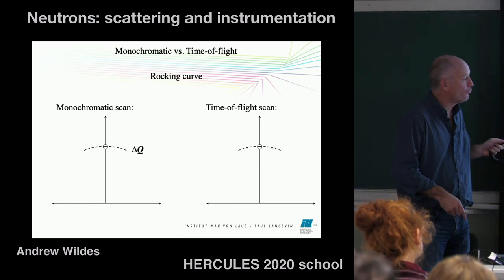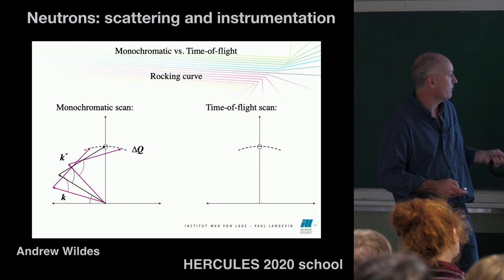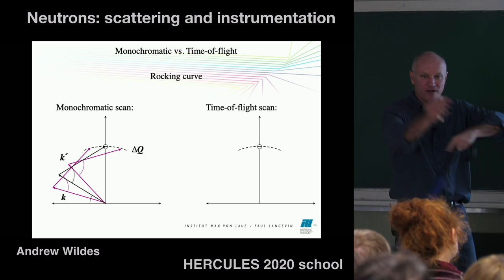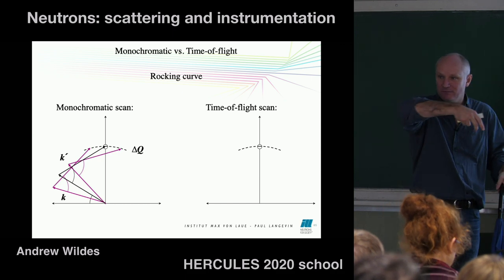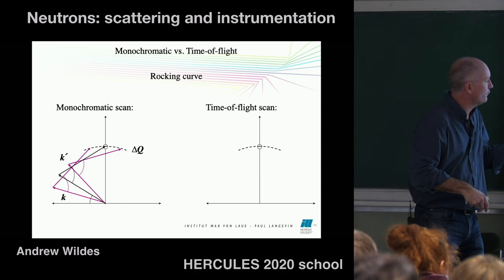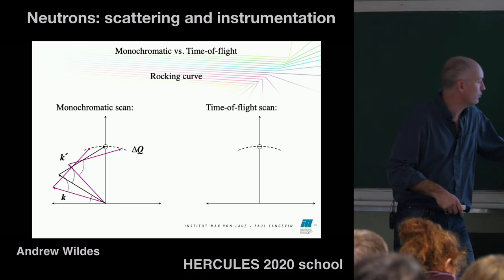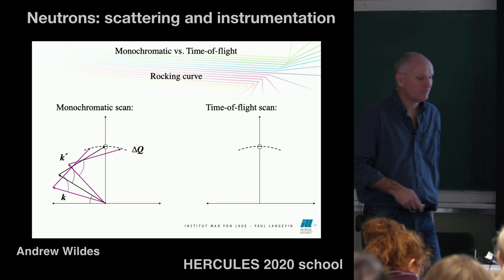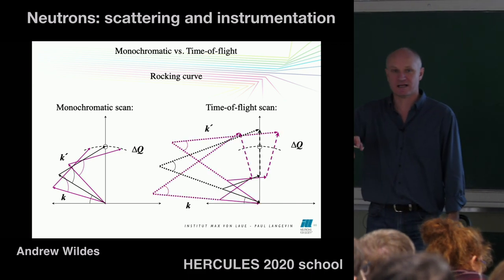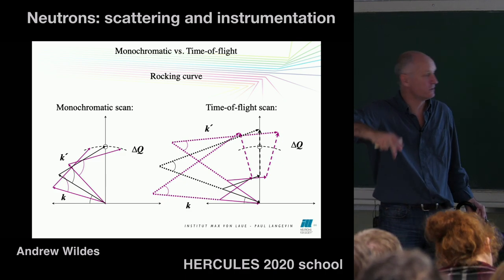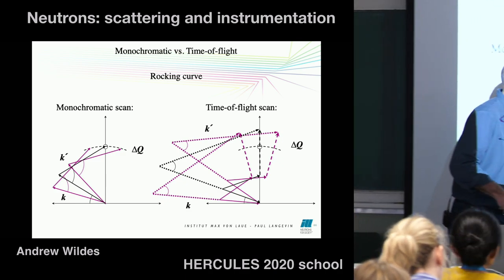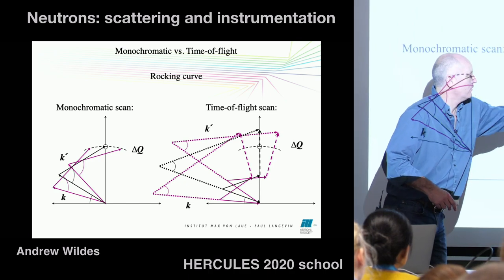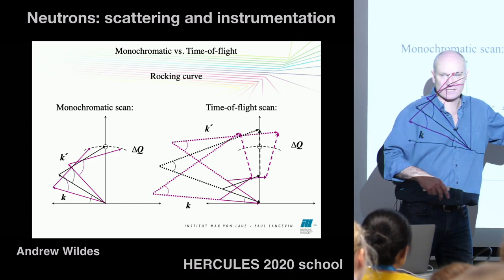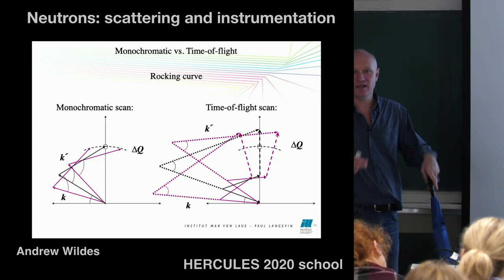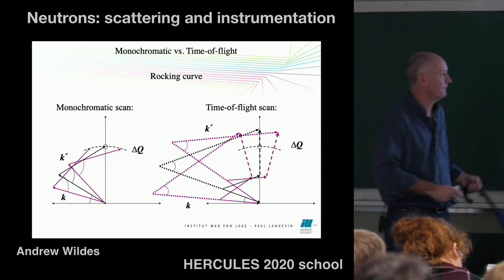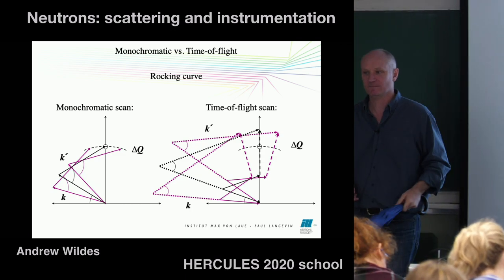If you want to do a rocking curve, in this particular case with a monochromatic scan, you would fix the angle of your detector and then you rotate the sample. That's called rocking the sample. And the trajectory you follow is this arc in reciprocal space, right? Your Q goes from here to here. In time of flight, you also have to rock your sample. There's no avoiding it. In either case, you've got to rock your sample. But one thing that's kind of advantageous here is you're selecting always this radial change as well, so you're covering quite a lot of reciprocal space. So that's kind of nice because you can get a reciprocal space map very, very quickly in a time of flight scan where you can't in a monochromatic scan.